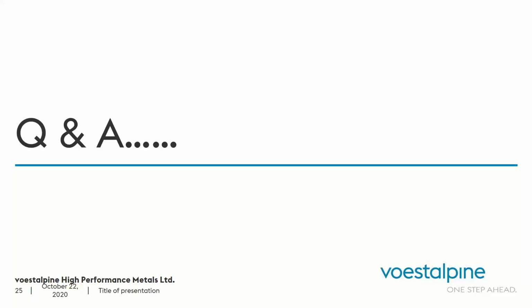Okay. Can the coating be removed for engineering changes? Yeah, good question. Absolutely. We have 2 ways of stripping the coating. The first way is chemically, and we've done that a number of times when, at the last minute, we've coated a tool, it's returned, and there's substantial engineering that has to be done to it. So it doesn't change the surface at all. If it's highly polished, it'll haze it up a little bit, but with a quick polish, that'll bring it up, and then we can recoat it.